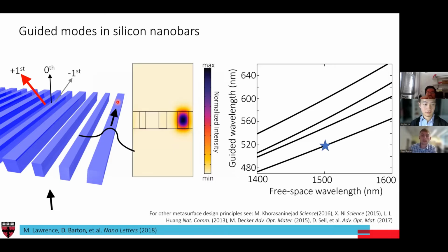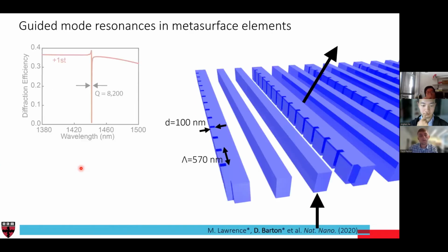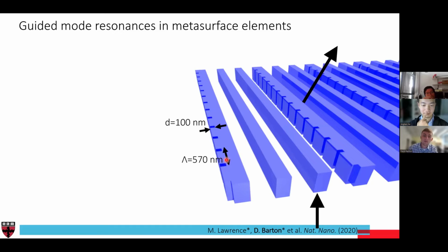So if we look at maybe 1500 nanometers, and I look at a cross section of this structure, here is what the mode looks like that's guided in and out of the page. We see that there are a whole series of guided modes that appear in individual bars, because the refractive index, in this case of silicon, is high enough to allow this guiding to happen. And so what we came up with was the ability to interact with these guided modes. If we include in these nanobars little grooves that appear periodically, the periodicity of this structuring corresponds to the guided mode wavelength of a mode within the nanobar.